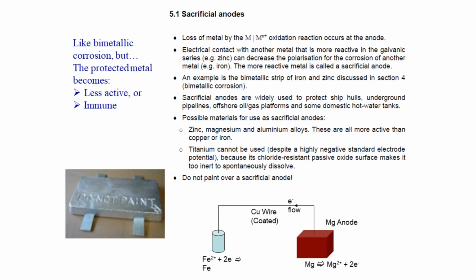So the other metal is protected by a sacrificial anode. Following the algebraic methods we looked at in section 4.1, we can work out whether the protected metal is expected to become simply less active and corrode more slowly, or even to become immune from corrosion. Which happens will depend on the kinetic parameters of both metals - the exchange current density, equilibrium potentials, etc. - and the areas of the two metals. So that's some work you might have to do.